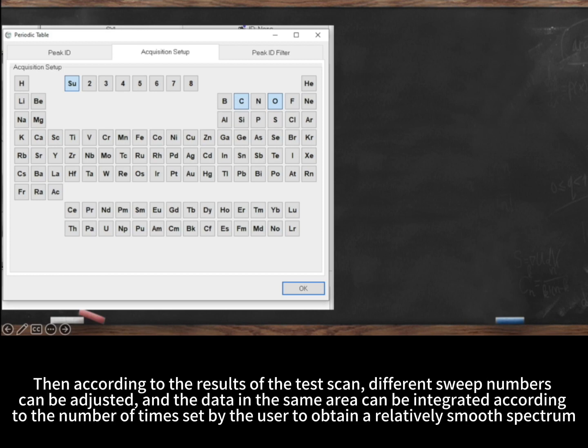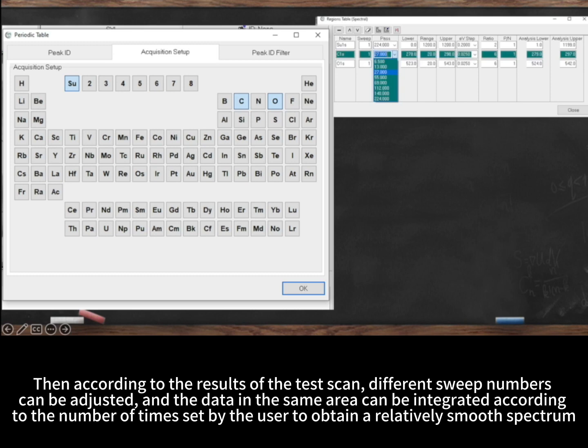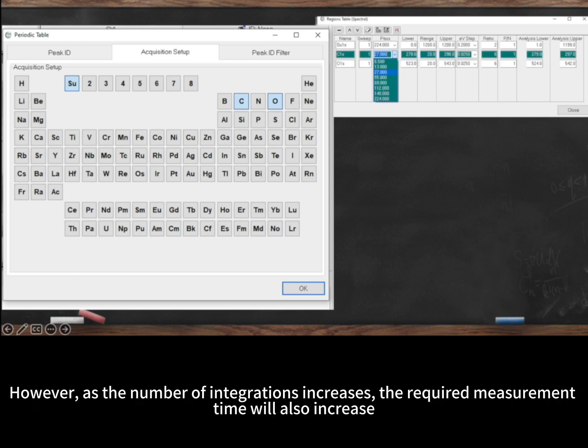Then, according to the results of the test scan, different sweep numbers can be adjusted, and the data in the same area can be integrated according to the number of times set by the user to obtain a relatively smooth spectrum. However, as the number of integrations increases, the required measurement time will also increase.